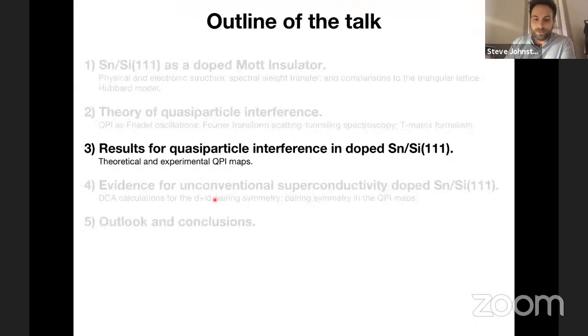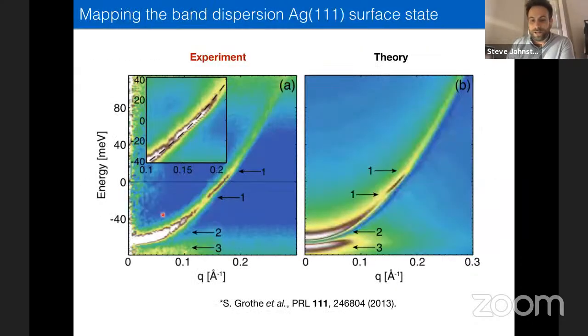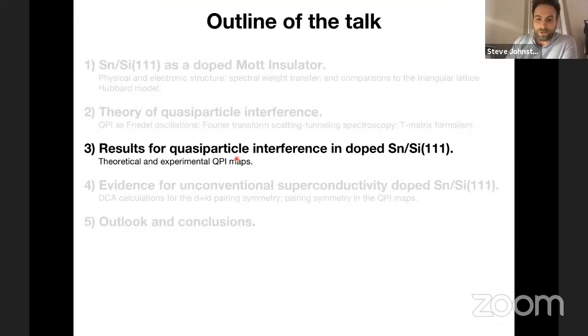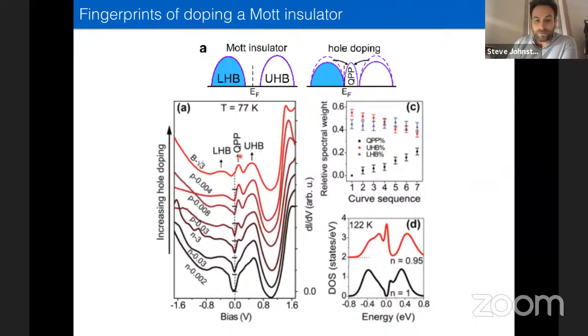Now, that being said, this parabolic band, you might ask why I do this. This is a nice simple case where I can just look at this and see that this is the parabolic dispersion. In this tin system that I'm going to show you, it's actually a bit more complicated. The Fermi surface is large enough that you start to see a lot of Umklapp scattering, and the patterns become quite complicated. And so that's why we need the theory to compare against. So with that in mind, again, I'm going to remind you, what we're trying to do is confirm that this peak that's emerging is actually a dispersive state, and that it has a dispersion that can be linked back to the band dispersion of the tin monolayer system, and not some incoherent impurity state.